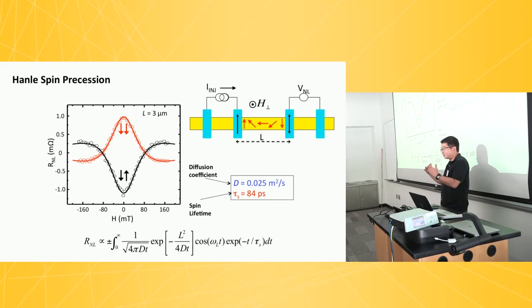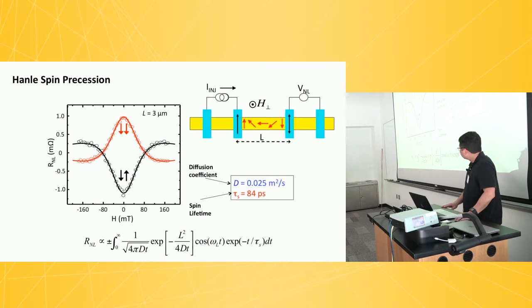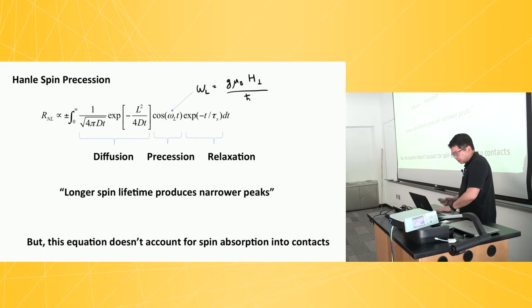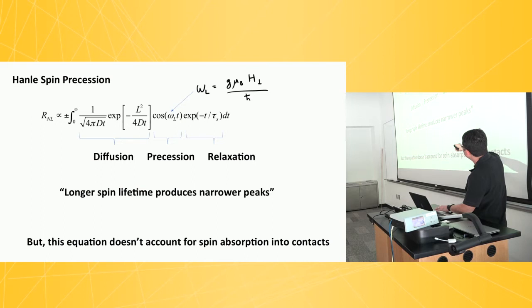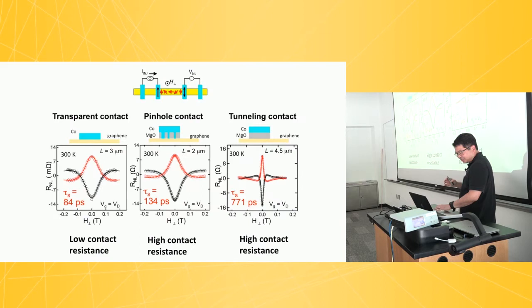When the first work was done out of the Netherlands group, they got like 100 picoseconds, so everything looks great. It even works at room temperature, but the lifetime seems too short. The thing that this equation we had here doesn't take into account is that these spins can actually get sucked back into the electrodes, like I told you early on. And let me just get to a punchline here.